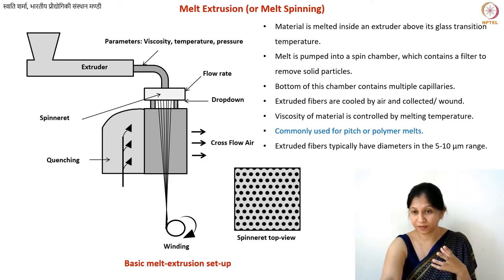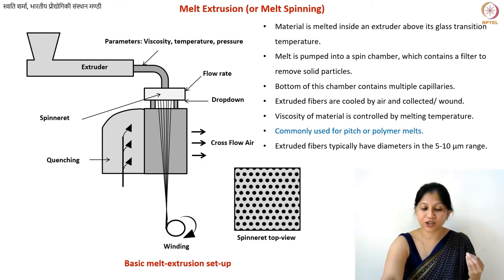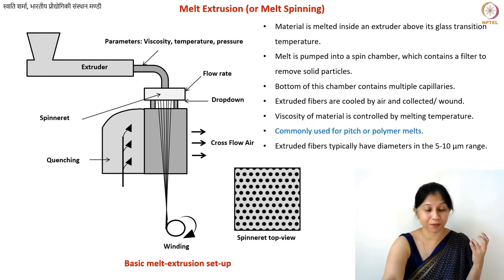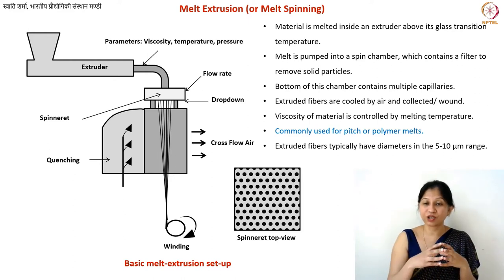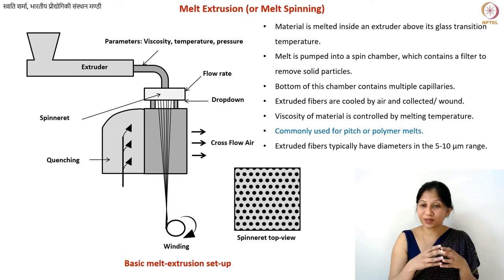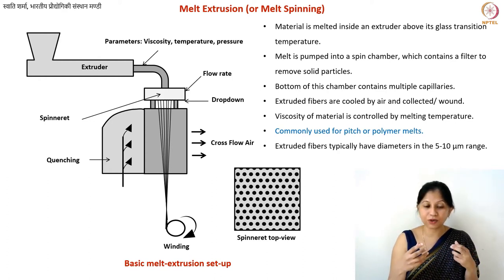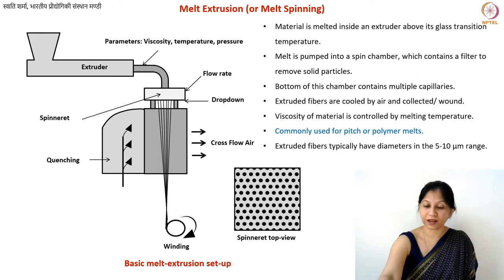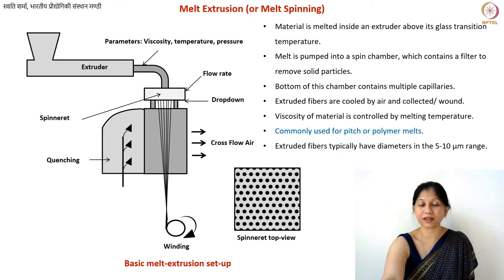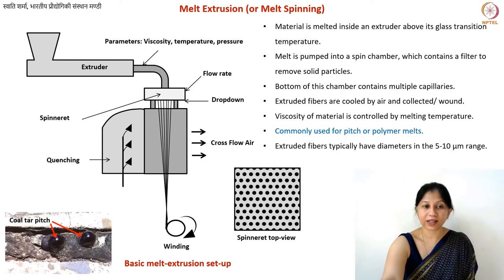After carbonization, fibers may be slightly smaller than 5 to 10 micrometers. The shrinkage patterns in fibers are also different from bulk industrial carbons — there is much more shrinkage in bulk due to greater mass loss. In fibers, the higher surface area means defects and byproducts can anneal out more easily, so you don't get as much shrinkage as in bulk materials.